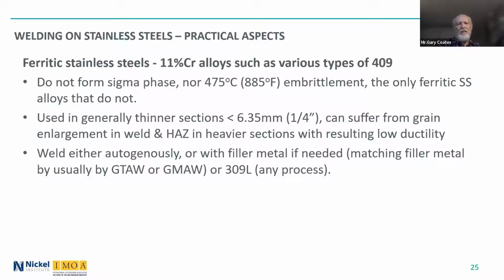Generally, you find them in thinner sections, less than 6 millimeter or quarter inch, but they can suffer from grain enlargement in the weld and heat affected zone in heavier sections, which results in low ductility. They can be welded autogenously or with filler metal if needed. And there are some matching filler metals where you're using them especially for automotive exhaust systems, which is high volume. If they can't be welded autogenously, they'll use a 409 type filler metal, and either gas tungsten arc or gas metal arc welding is used, and 309 can also be used on these alloys.